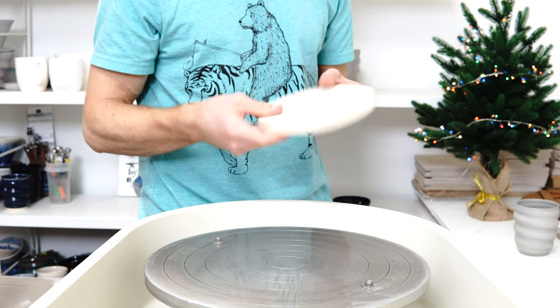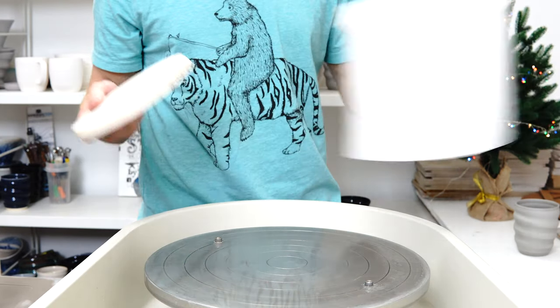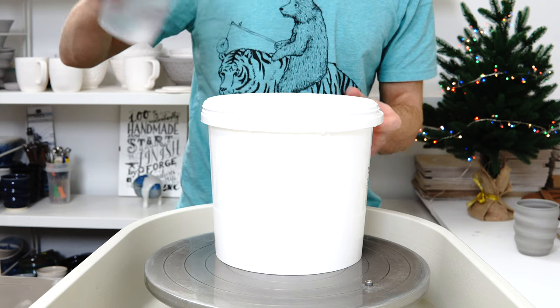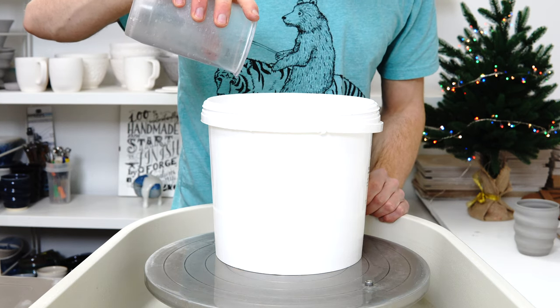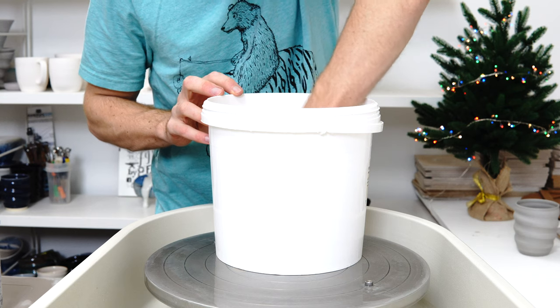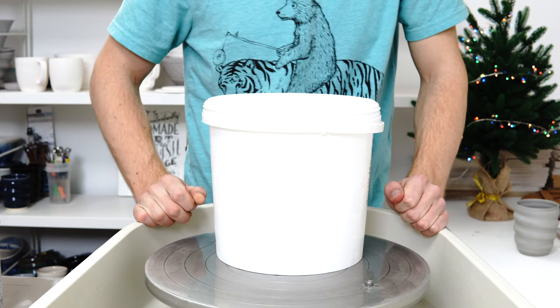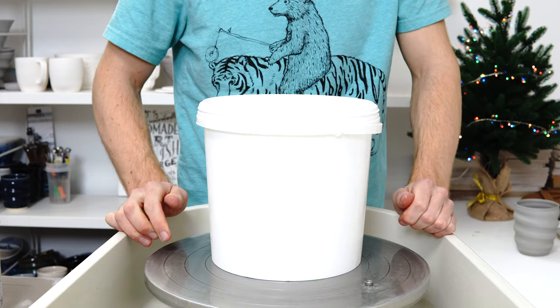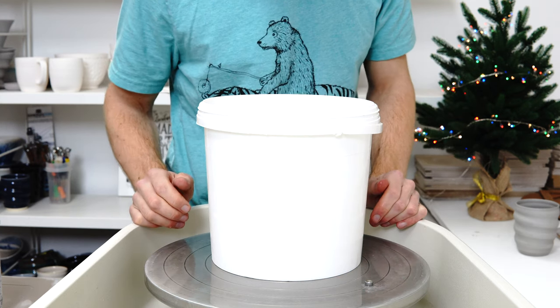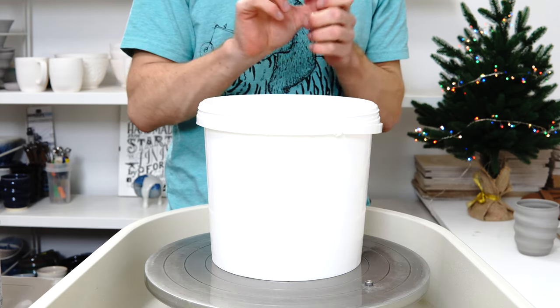I think you should be able to completely rehydrate it. I've got a little bit of plaster — just normal plaster of Paris — and a tightly sealing plastic pot. I pour in 150ml of water, which might be too much as it's floating in there. The mug should need about 70ml of water to rehydrate back to plastic clay.